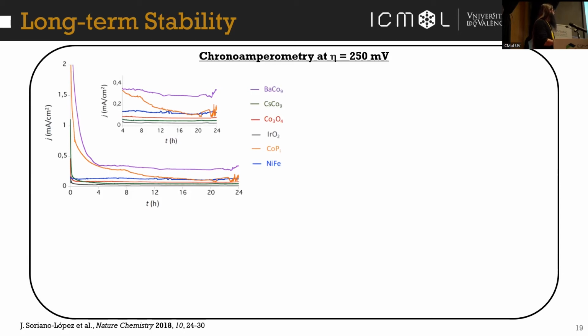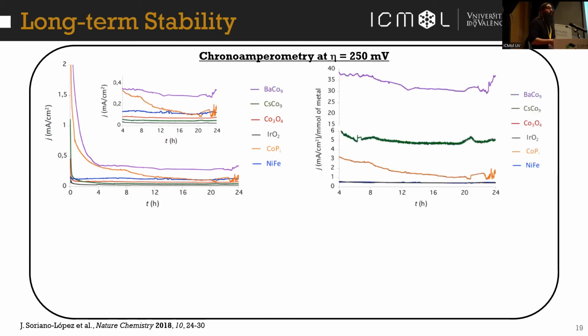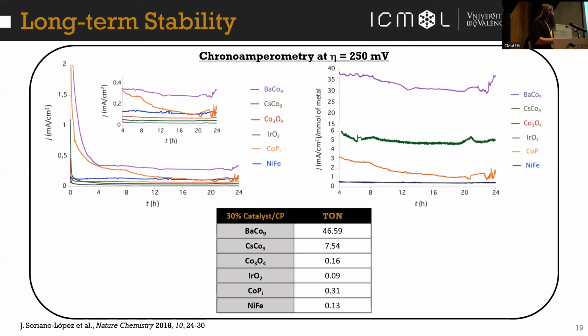And also if we compare the activity, taking into account the moles of metals that we use in each electrode, we can see that none of them could match the activity of the barium cobalt-9. And also we estimated the turnover numbers, and we can see that, again, the barium cobalt-9 has superior performance